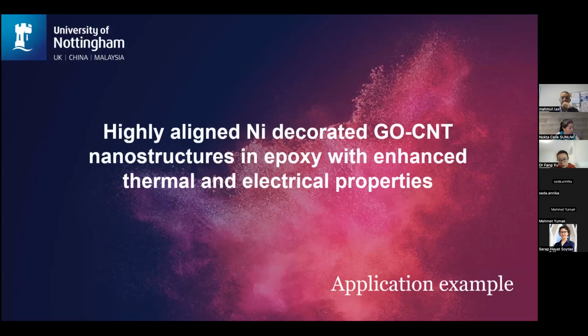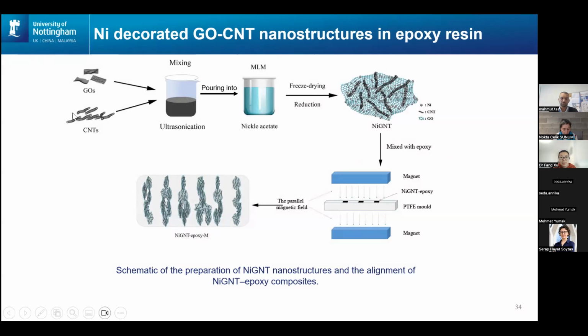This is one example. Another example we'd like to talk about is nickel decorated GO-CNT mixed with epoxy resin. There's not much we can do when preparing PEK composites because it's not in melted form, but for epoxy resin there are more options to consider. The first part is still to get the nickel coated GNT, then we mix this structure with epoxy resin, because nickel is magnetic.